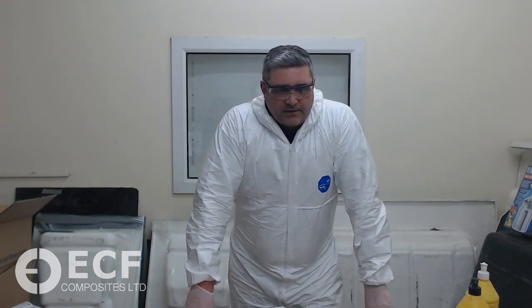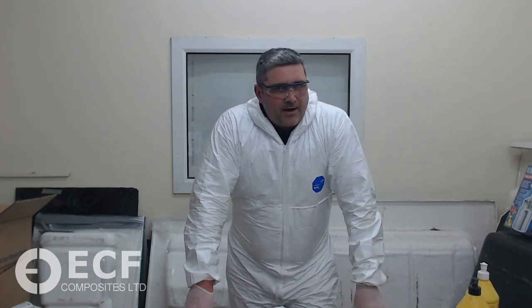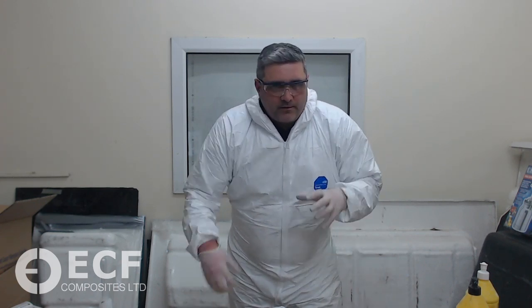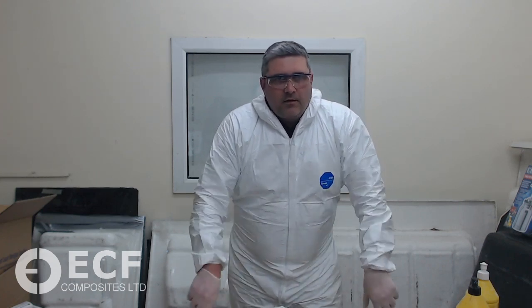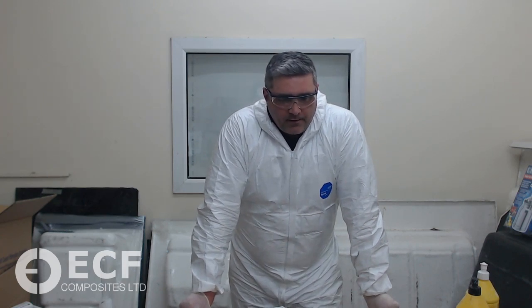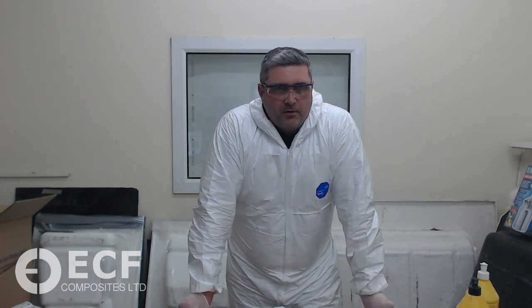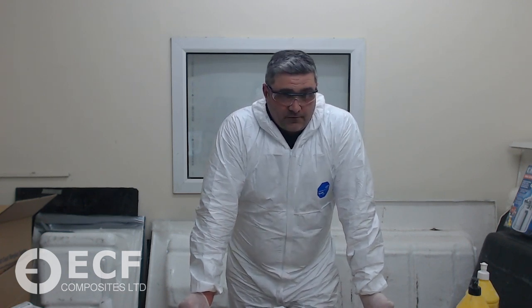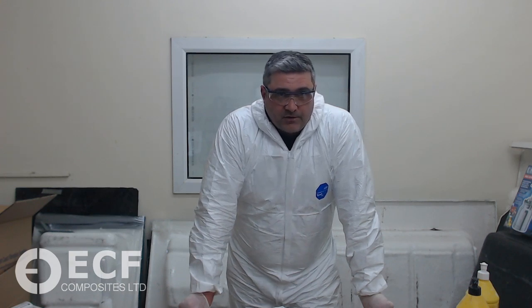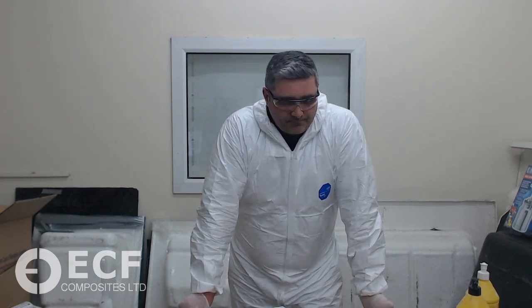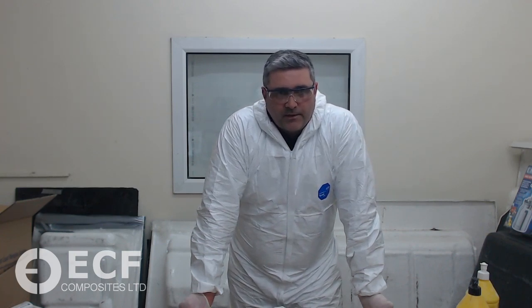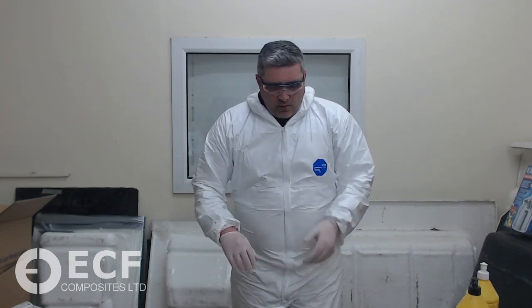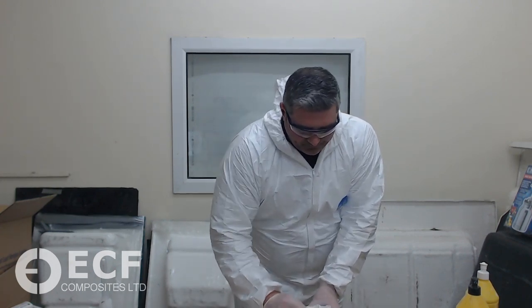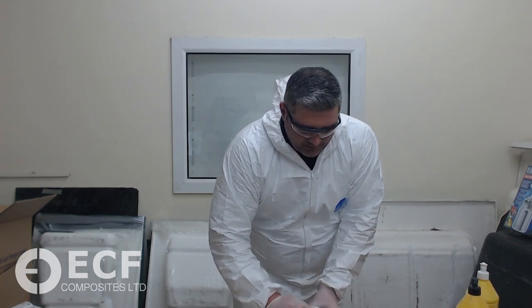You can, but I've also seen products which have been thoroughly sanded back of the old flow coat, reapplied, and then after a few extreme seasons, cold weather, hot weather, and this contraction, expansion, you start to see that new top coat start to peel away. So it depends on what you're doing, but I would probably only put the wax in the very last layer, usually in your gel coat, to convert it to what's known as a flow coat, or some people refer to it as a top coat. But we do have those ready-made, so you can buy gel coats and flow coats separately. But if you let us know a little bit more about why you're doing that, I might come up with another solution for you. At a guess, I'm guessing you're finishing your boat with it.